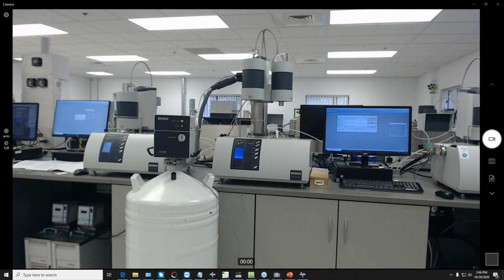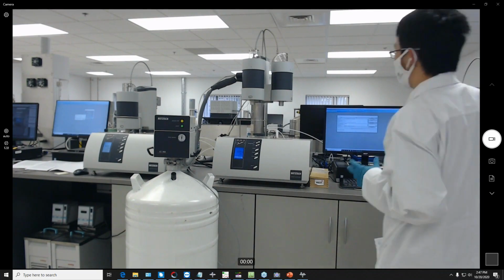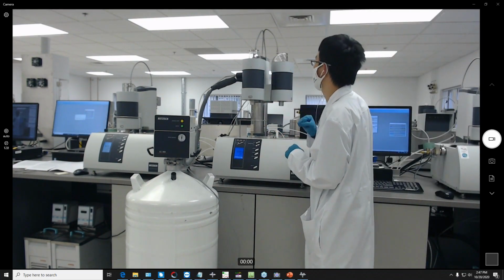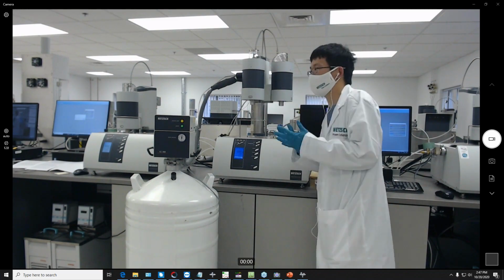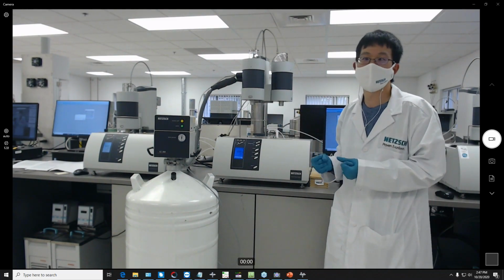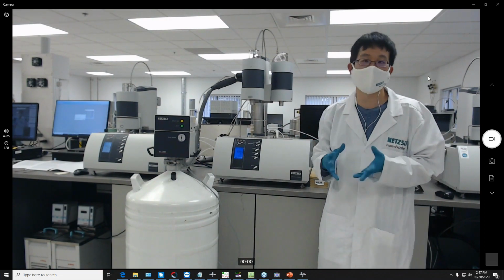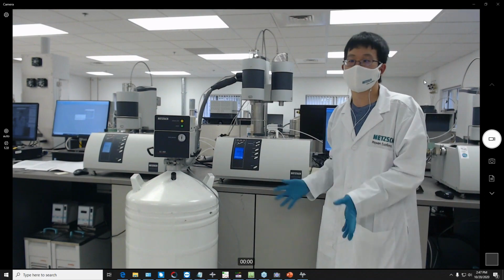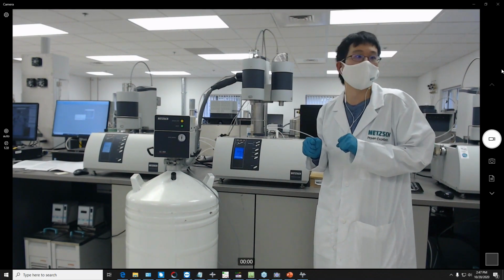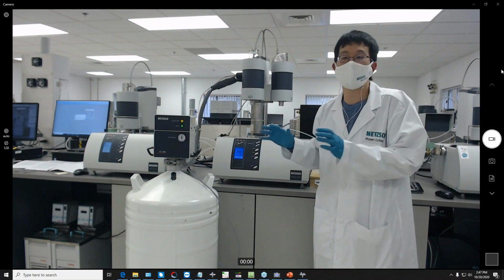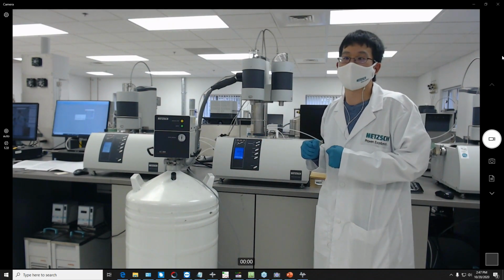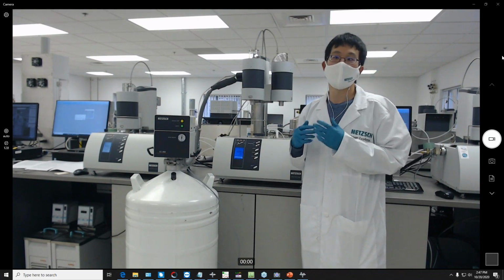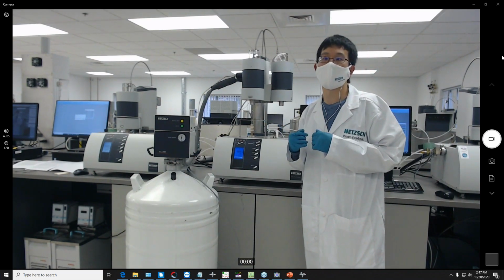So using a purge of 50 milliliters of nitrogen and 20 milliliters of protective, how much time is required for filling the instrument with purge? So roughly our total system balance and furnace system is about 3 liters in volume. So usually I'll give it at least about a 10 to 15 minute purge in order to get all the atmospheric gases out of the system. You can always increase your flow rates to push out those atmospheric gases faster. But if you're just using the default 70 milliliters per minute, I would recommend a 10 to 15 minute wait.